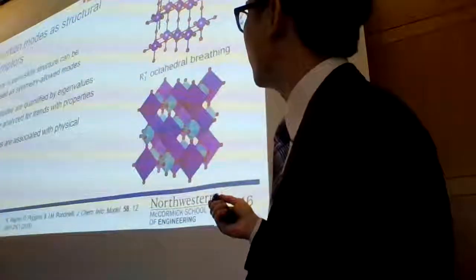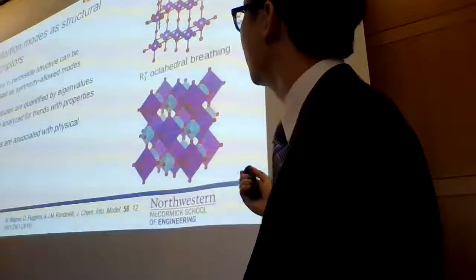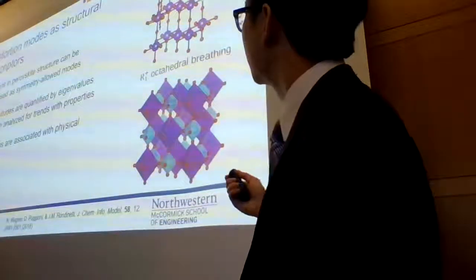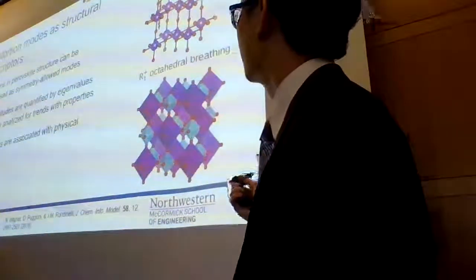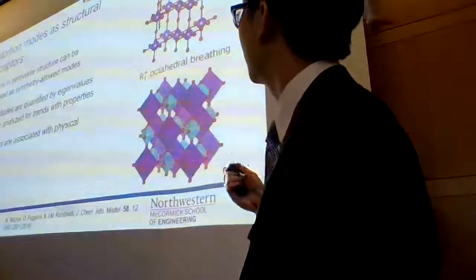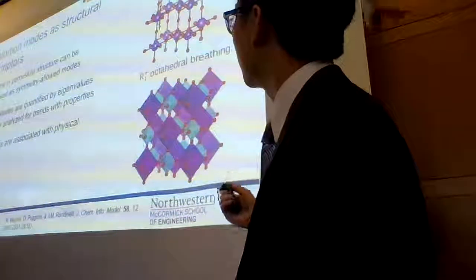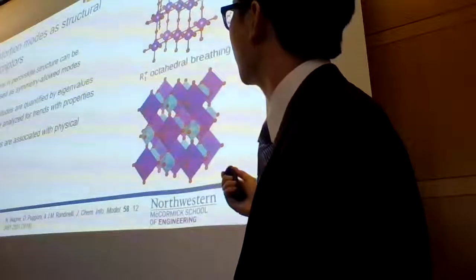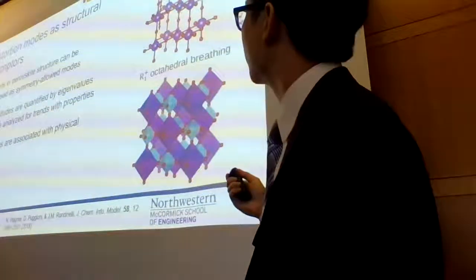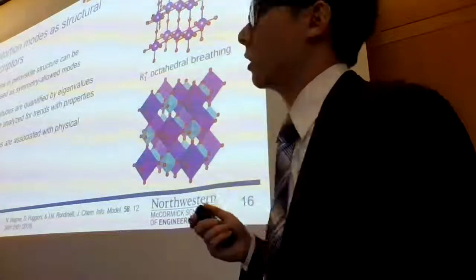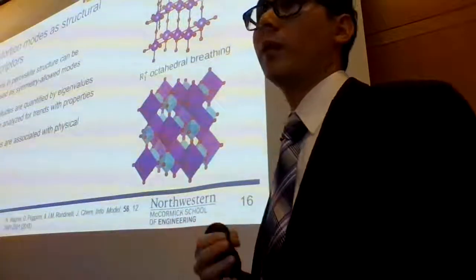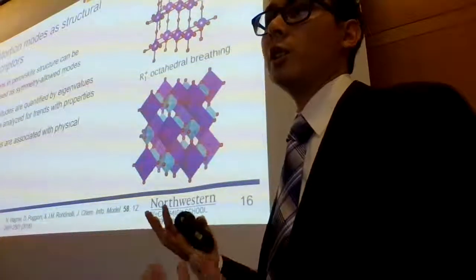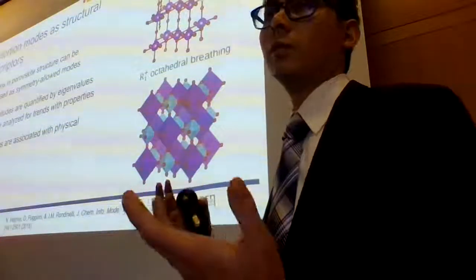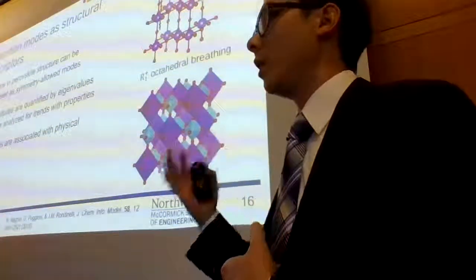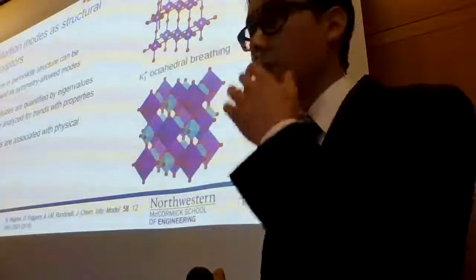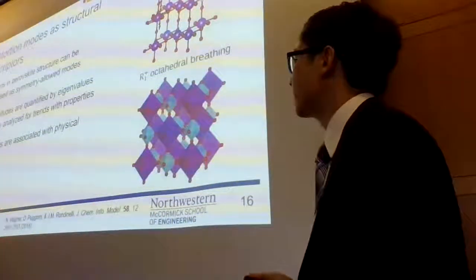Two of the distortions that I'll highlight here are related to physical mechanisms that I just mentioned. This A-type Jahn-Teller is related to the Jahn-Teller mechanism possibly mentioned earlier, where along the apical bond lengths you have an alternating lengthening and shortening, and then you have the reverse in the in-plane lengthening and shortening. That leads to another splitting of the eg orbitals in this material, which could lead to a sudden inability to conduct electrons. So that's one possible mechanism that physically makes sense.